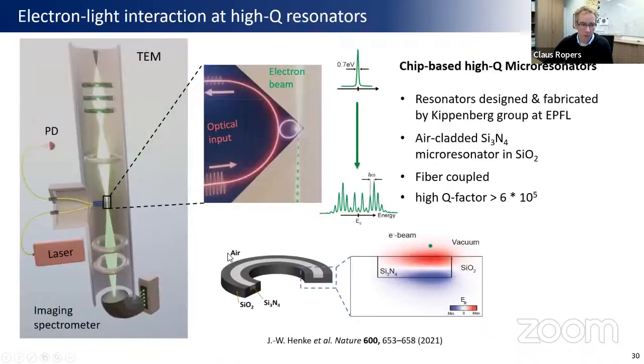Yeah, most recently, we've actually gone even one step further to make sure that the electrons actually can strongly couple to just a single mode of the optical field. And to this end, we've teamed up with the Kippenberg group at EPFL to fabricate specifically designed optical resonators, which allow for phase matching of this interaction, electrons to the cavity modes, which have well-defined optical near field going into vacuum. So they have a vacuum interface where we can pass the electron beams through, and where the quality factor of these resonators is substantially higher than for the other structures that we had studied before. So in this case, approaching 10 to the 6, which means that even weak optical excitation, so continuous wave excitation, actually leads to sufficiently strong coupling to affect the electrons here.